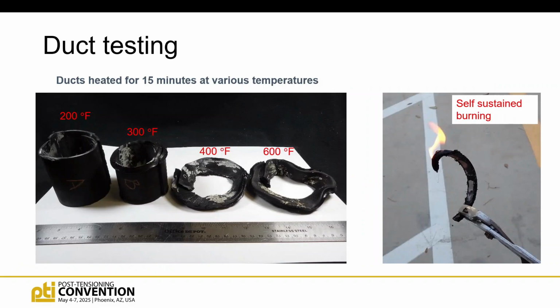I mentioned we tried to use the ducts as a way to determine how hot the tendons got. So once again, we cooked them in the oven at various temperatures to see if we could mimic what we found, and we never did get there, right? Because you saw that one where it was dripping off. Well, we didn't get there even at 600 degrees Fahrenheit, and that was cooked for an hour.